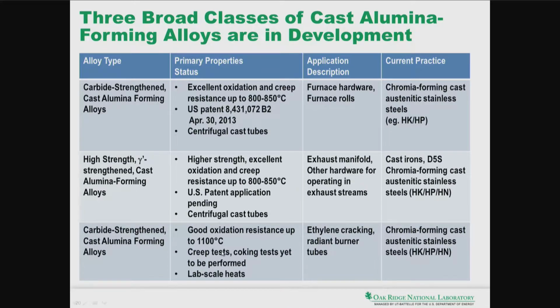The third class of alloys that we really are aiming towards the ethylene cracking and radiant burner tube applications, where the temperatures are approaching about 1100 C. As I will show you later, we have identified some alloy compositions within the granted US patent that would be able to perform at these temperatures.